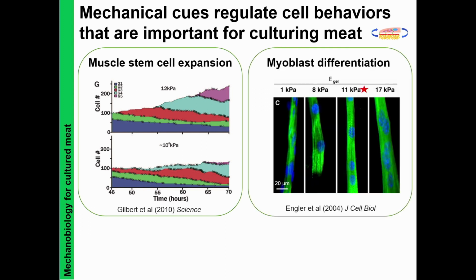Also differentiation, we know, can be driven by mechanical factors as well. This is some seminal work from Adam Engler, when he was in the lab of Dennis Discher, looking at the differentiation and myotube formation of C2C12 mouse myoblasts. And you can see on a substrate of about 11 kilopascals, the myotubes are very beautifully showing aligned nuclei and striations, suggesting that this is a more ideal substrate stiffness than a softer or stiffer matrix. So these are the muscle cells.